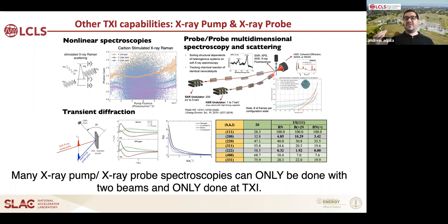You can sort either on the spectral data, a few photons, or sort on your diffraction data. And if all the particles are the same, your spectral data is going to give you a natural time coordinate of the reaction. Then you can correlate what's going on at the surface of this nanocatalytic particle as a function of time, which is really cool, where you're not really triggering, but you're collecting enough useful data in different dimensionalities to record what's going on in time without a time axis.